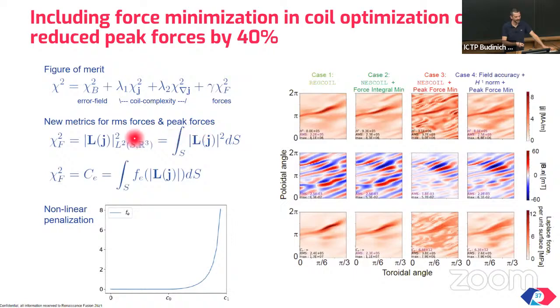a Laplace force metric, either the surface average of the root mean square, or you can introduce a nonlinear penalty. Basically, forces below some value are allowed, between a soft and a hard limit they are penalized, and above a hard limit, the penalty is infinite, so the forces are completely forbidden.